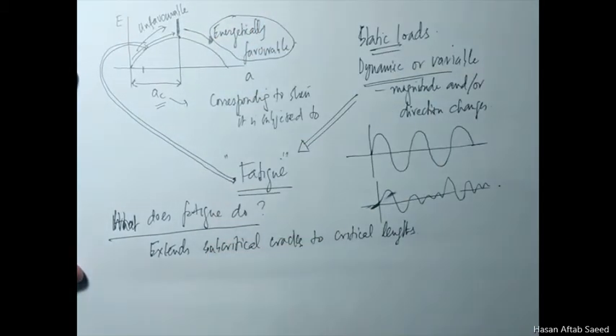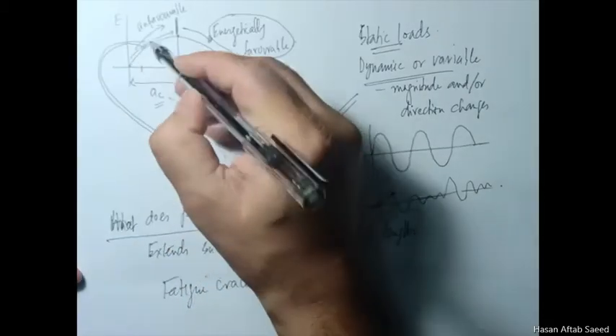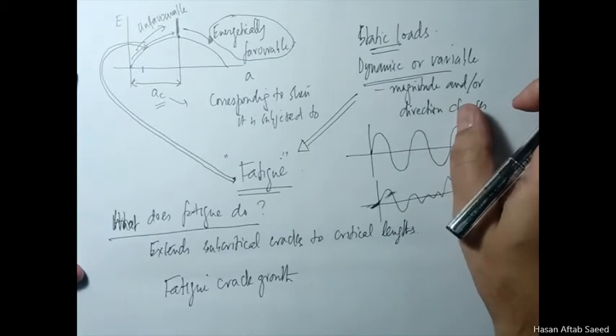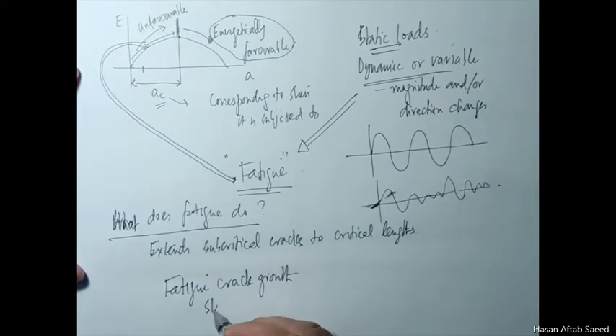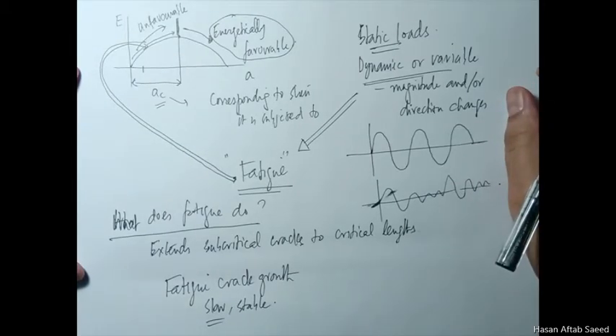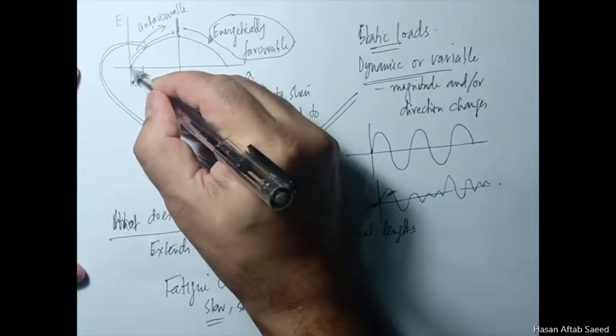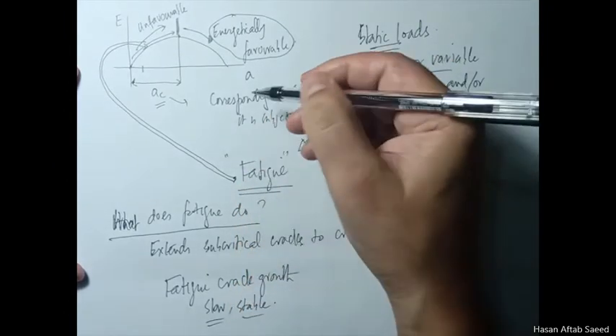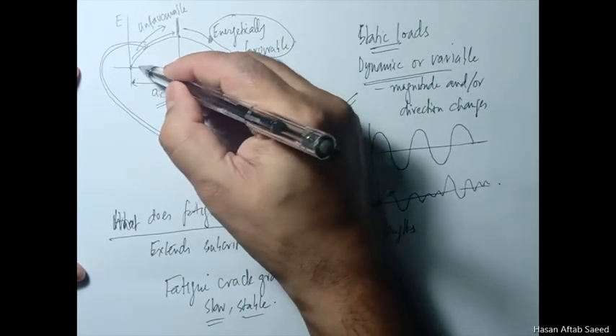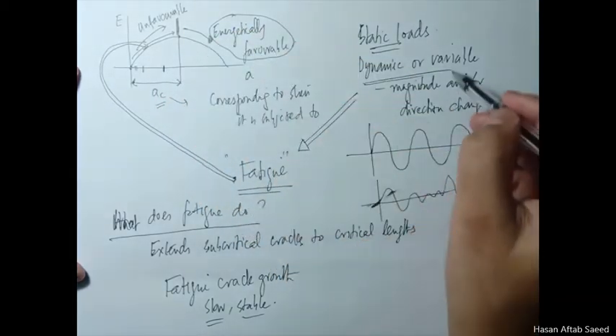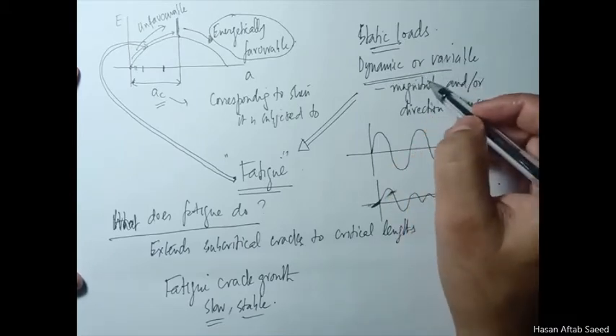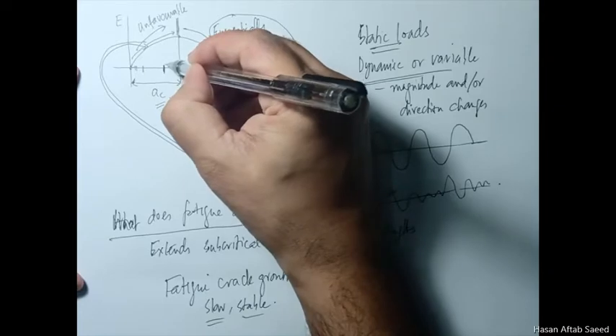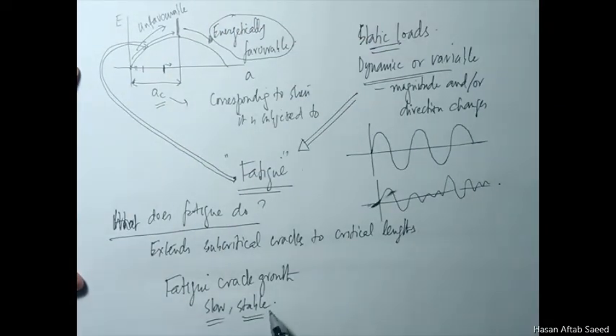This is the dividing line. The fatigue crack growth, the growth from here to here, this region, is slow, stable. By slow, I mean it could take thousands or millions of revolutions for it to achieve this goal of taking a subcritical crack to the critical size. Stable. If fatigue takes such crack length from 0 or somewhere around here to this point and then stops, whatever is happening, we stop the dynamic loading on the body, then the crack stops here. It doesn't extend one bit.